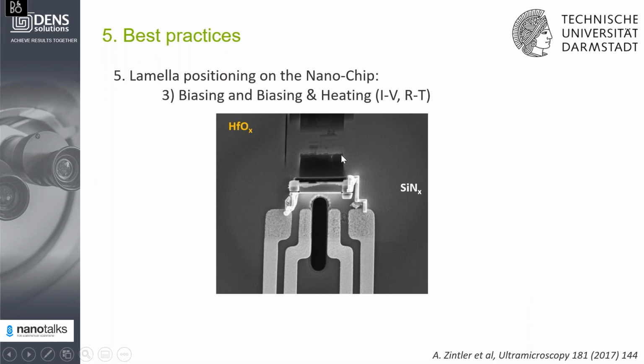So basically what you see here is a window, and this is when the lamella was milled, then we milled away part of the silicon nitride. But again, the silicon nitride is just a support. It supports the rest of the structures and the lamella. All the heating and biasing happens in a different place. So it is possible to make trenches and cut silicon nitride, and it will not affect the functionality. Okay.